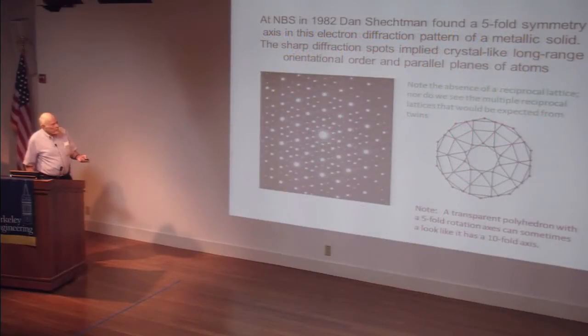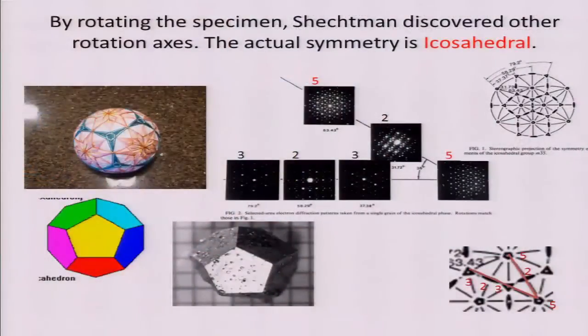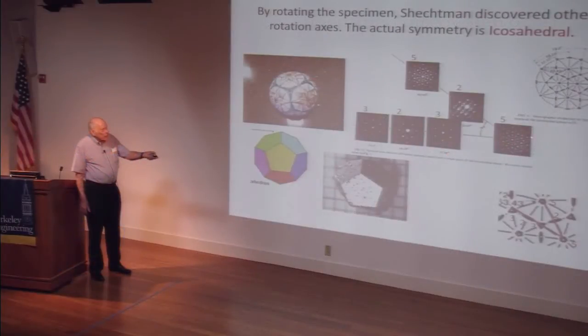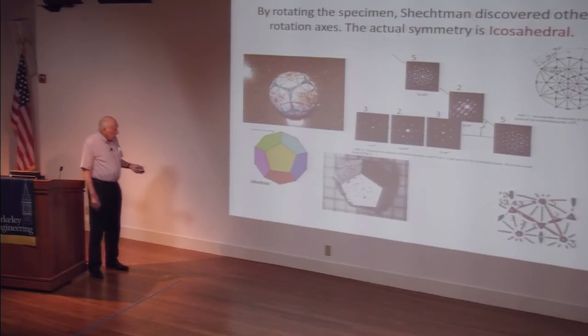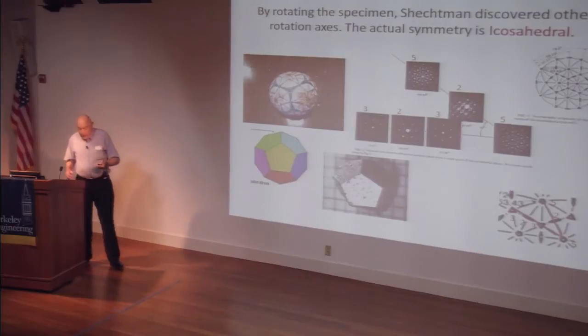When he rotates, he found that he had the five-fold pattern there. He rotated in one direction, 5, 2, 5. He rotated in another direction, 5, 3, 2, 3. And here we have 5, 3, 2, 3, 5, to 5. This is a ball I got in Japan. Here is an icosahedron, 5 to 5, 5, 3 to 3, back to 5. And here is a quasi-crystal, same shape as this. So it really...